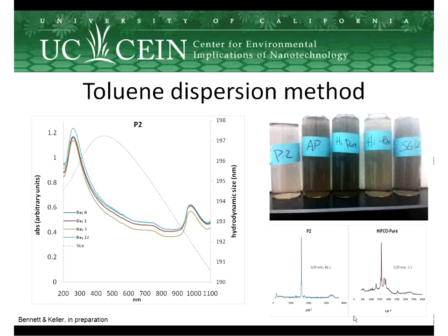So that may be a two-step process, but it's still a question whether the toluene will have some or no implication. And so what we see is that their size kind of is in a range that we would like to see most of them. This is the size distribution, really. So what we're seeing is that this is the wavelength, and this is the size distribution, so it refers to that one over here. And so we see that the carbon nanotubes are in the order of a few, like 200 nanometers.